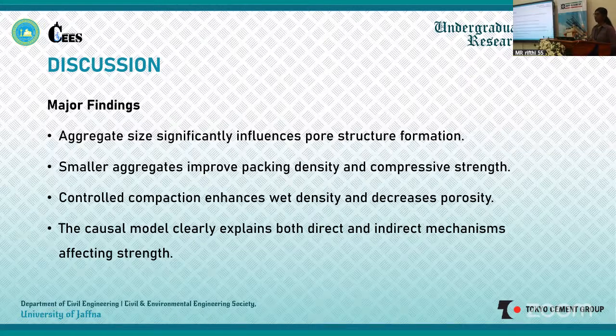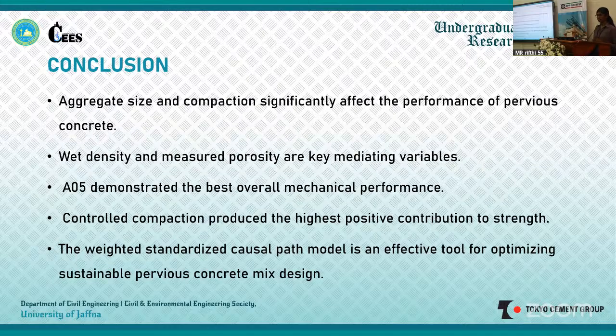In conclusion, aggregate size and compaction significantly affect the performance of the pervious concrete. The wet density and measured porosity are the key mediating variables. Here, the A05 demonstrates the best overall value. And finally, the weighted standardized causal path model is an effective tool for optimizing the sustainable pervious concrete mix design.